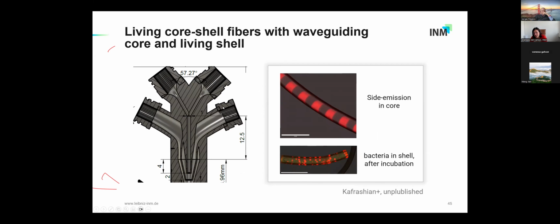Then we have the one on the right. This inlet is for the bacteria ink or for the bioink, and this inlet here is for the protective layers. And we can prepare these waveguides with the 3 layers to make the system work. Here you can see the inner layer, sorry, the core layer with the side emission, and here you see bacteria colonies outside which have been grown after activation.